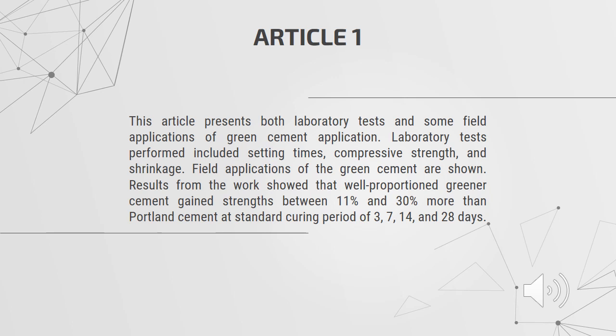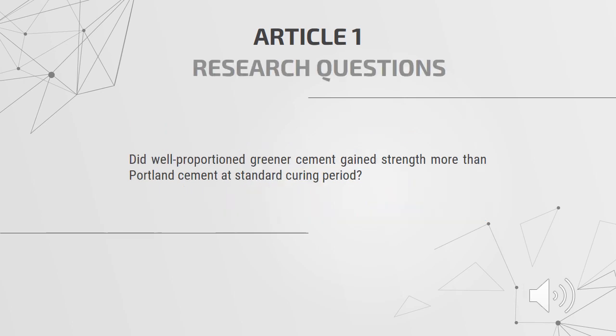Basically, Article 1 is about green cement application and utilization in building projects. The researcher performed 2 tests, which are a laboratory test and a field application. In the laboratory tests, they performed 3 types of tests, which are setting times, compressive strength, and shrinkage. At the end of these tests, they concluded that greener cement gains 11% to 30% more strength than Portland cement at standard curing periods of 3, 7, 14, and 28 days. In this article, the researcher asked: does well-proportioned greener cement gain more strength than Portland cement at standard curing periods?